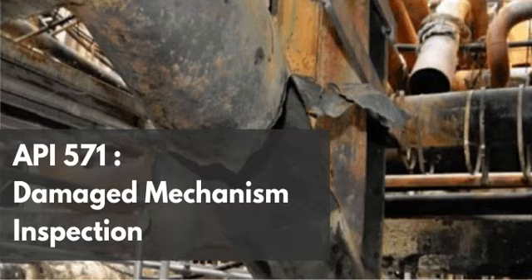The guidelines explicitly offer material alternatives for exactly this reason. If PWHT is not viable, use effective barrier coatings or upgrade to solid or clad 300 series stainless steel, alloy 400, or other corrosion-resistant alloys. It's the ultimate calculation of life cycle engineering economics.